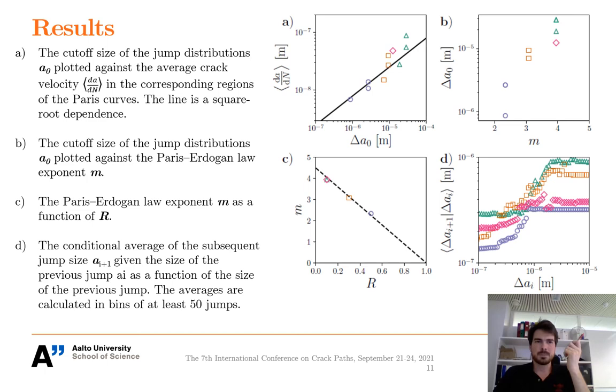So, what we find while following in details the crack tip growth is that the crack tip undergoes intermittent motion. These steps have a size distribution which is characterized by a particular power law exponent, roughly 2, with an increasing cutoff. The exponent value has no theoretical comparison in models of crack propagation in brittle materials, where the theory of depinning transition is applied. The experimentally found cutoff increases with the crack advancement, and thus, the step size and the typical crack growth rate averaged over long times, which relates the size distribution to the crack growth law, the Paris-Erdogan law. On short scale, the dynamics exhibit correlations such that they imply pinning-like dynamics, but with time and crack growth, this gets washed out in analog to the average Paris-like dependence on the velocity on delta K, which in spirit assumes Markovian memoryless dynamics. Thank you for your attention.